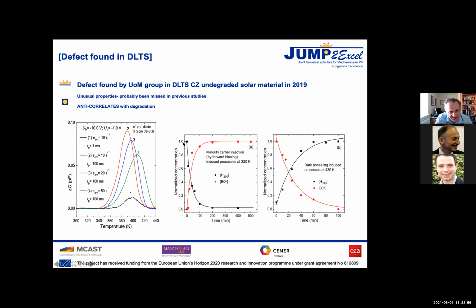So basically, we've extracted this from minority carrier lifetime, and we find that as the degradation occurs, this defect disappears. And the same on a shorter scale here. You can see that we've expanded the scale out. You see an almost perfect anti-correlation. So what we think is happening is that the state we see, which occurs in the as-manufactured silicon, is a precursor to the state that does the degradation.